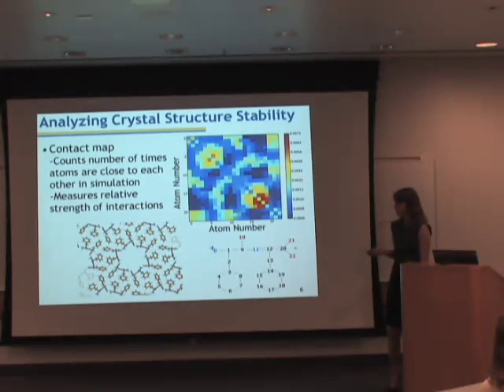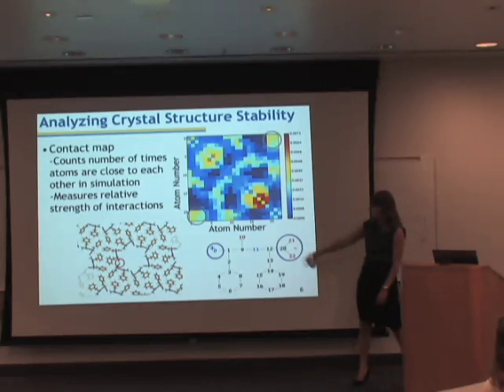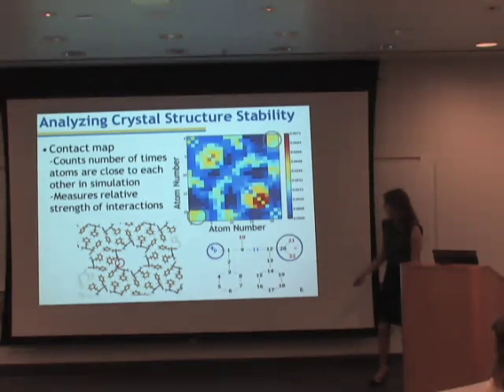diphenylalanine nanotubes form. So we looked for electrostatic interactions between the charged ends, and that corresponds to interactions between the 0 atom here and these atoms 20, 21, and 22, which corresponds to these areas circled in gray on the contact map. What we find is that while there is some degree of interaction between these charged ends, they don't represent the strongest amount of interaction between the peptides.